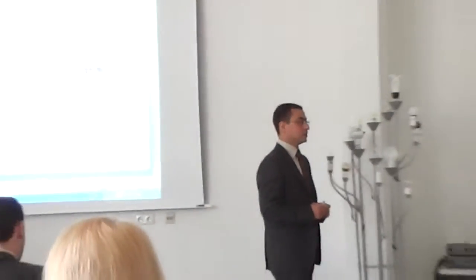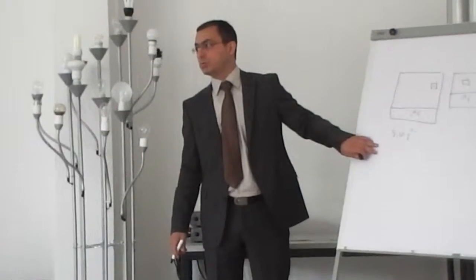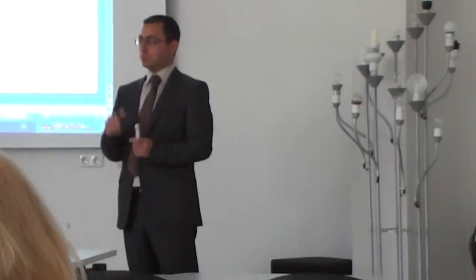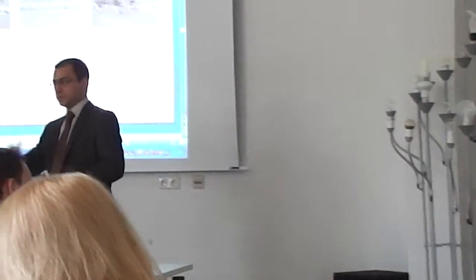You have to be honest. One question regarding your self-healing and particles. Did you try to identify active nanoparticles, how they could contribute to the self-healing process? In the case of silicium dioxide nanoparticles, I wrote a mechanism. There is a possibility of formation of this ion, which can react with aluminum in order to form an aluminum silicate layer. This aluminum silicate layer looks like a self-healing layer because it improves the barrier property of the silicate films and gives less corrosion. We can go into more detail on that.